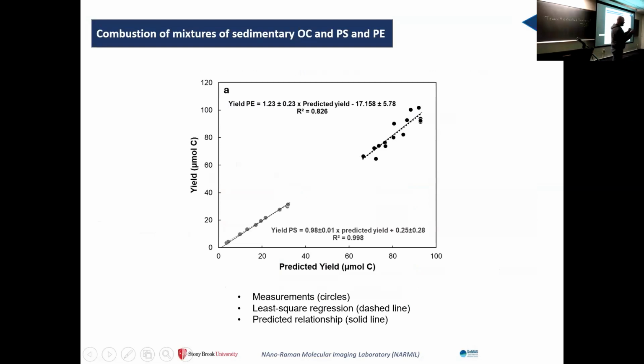So the values that the machine gave us are the circles. The least squares regression is the dashed line, and our predicted relationship is the solid line. Our predicted relationship is what mathematics is telling us is supposed to be there by conservation of mass. Any atom of carbon that we put there should be at the end also. And you can see here how our experimental results fall on top of our predicted relationship. So that is telling us that the machine we use is combusting all these carbon atoms and producing this result. And we assume that all carbon is from biogenic material, which we know now is not true.